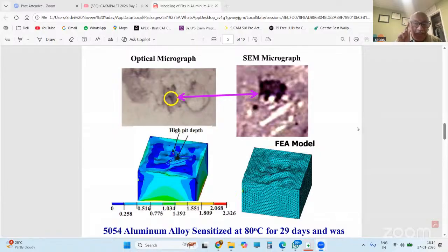The aluminum alloy was subjected to a harsh environment for one day at 80 degrees centigrade. This is to initiate pitting. And this is what happens after 29 days. After one day we cleaned it and kept it aside. So this is how it is, a continuous degradation. Although we think we have stopped it, we didn't. Next, please.